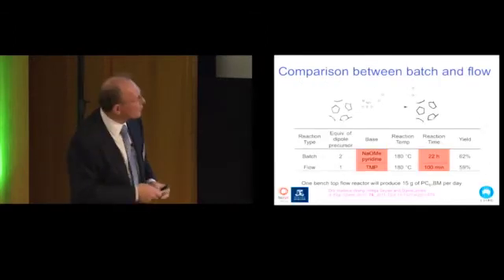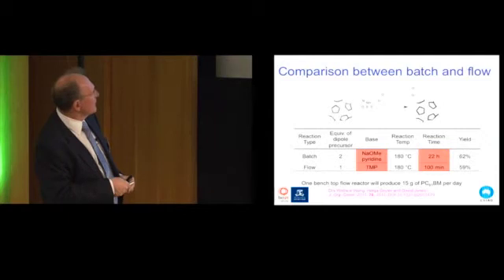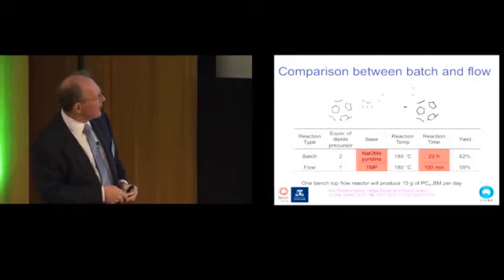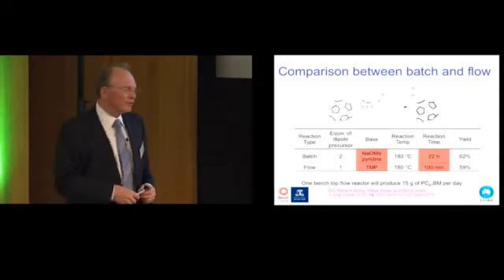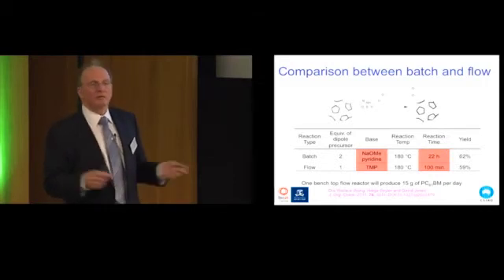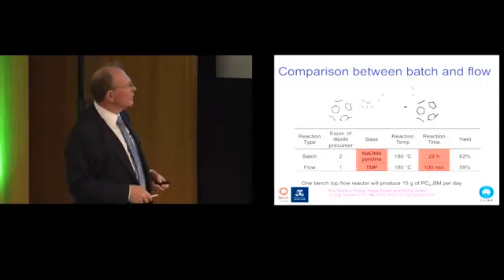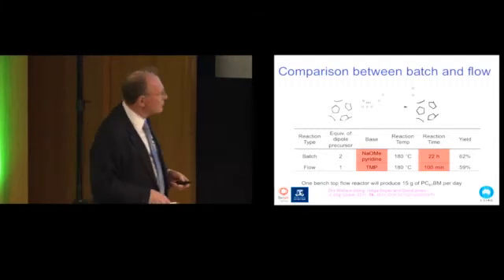And let me just show you the result. So if we make it by flow chemistry in 100 minutes, we can make the same amount as it takes 22 hours in batch chemistry and in the same yields. And so in one day, we can produce 15 grams of this material, and that's large enough to print 1,500 square meters of a printed solar cell, which I shall show you. So we can now make large enough amounts to use for printing.